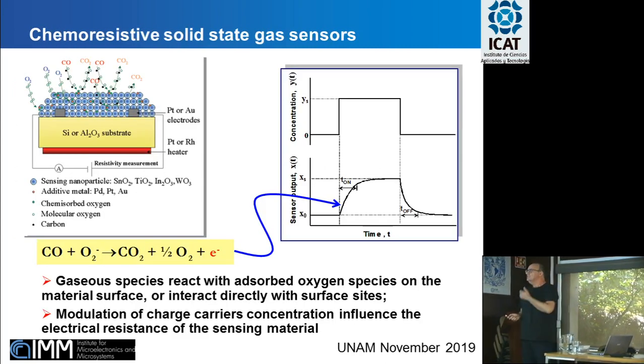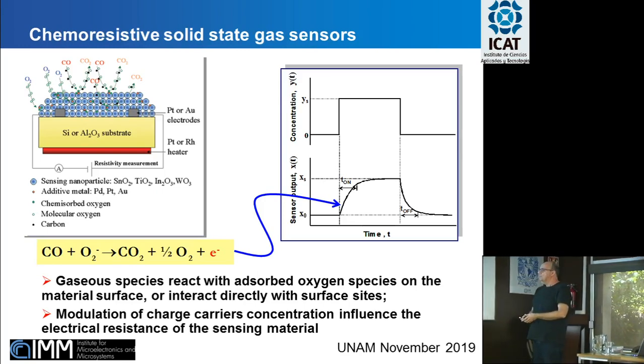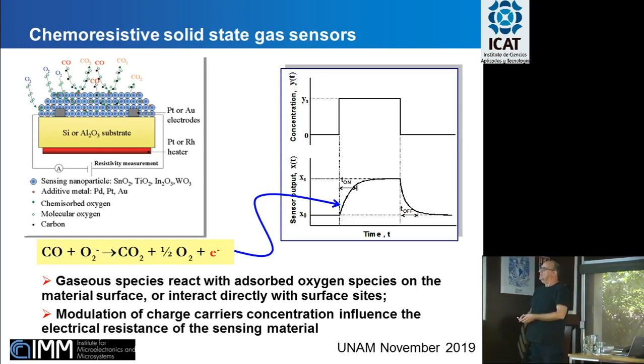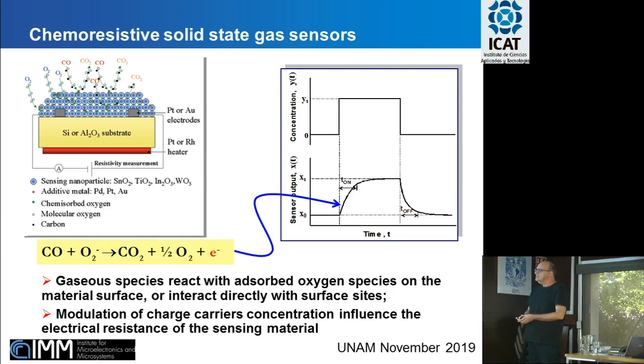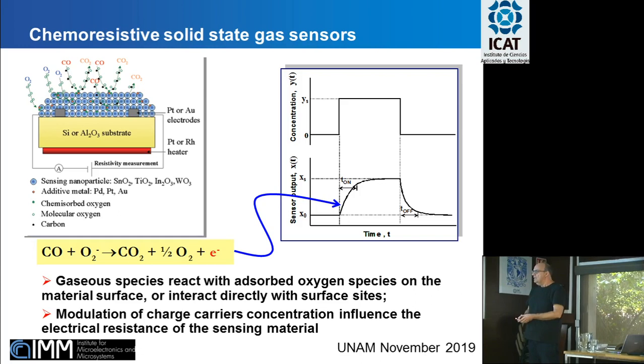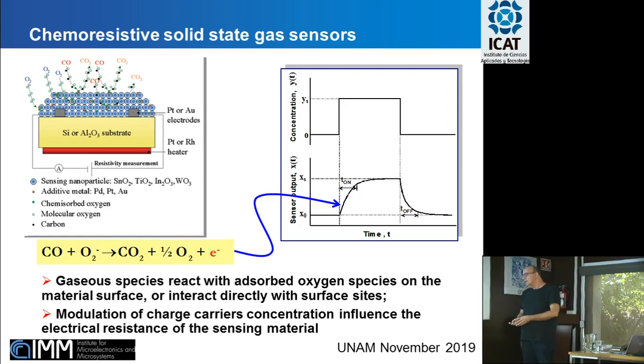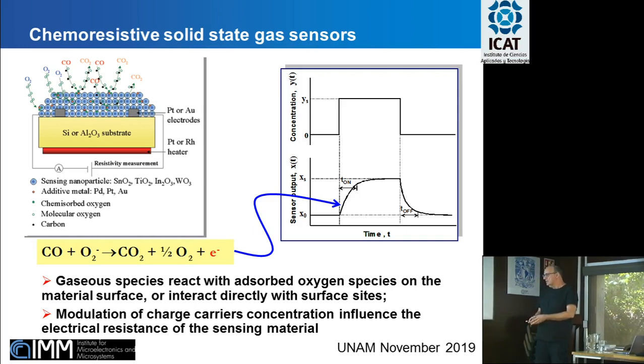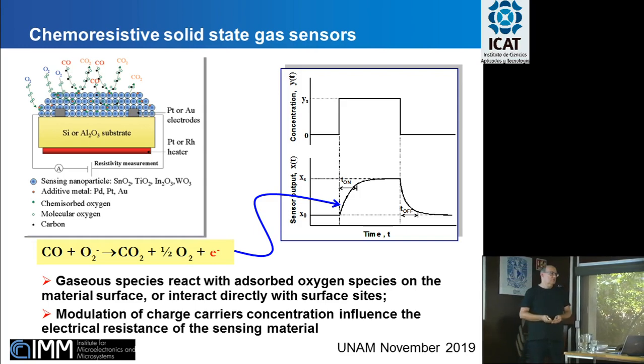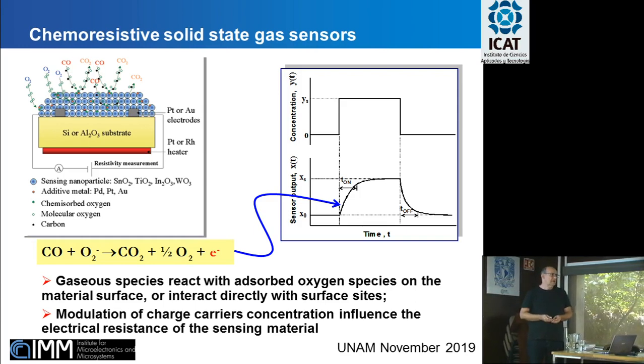So, in chemoresistive solid-state gas sensors, what happens is that we have the substrate, an active material, and the gaseous molecules which interact with the surface of the active material. Electrons are depleted from the active material, and when a gaseous analyte is reacting with our sensor, these electrons are given back to the material. This means that we have a modulation of the charge carrier concentration.